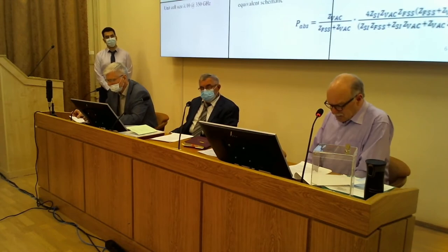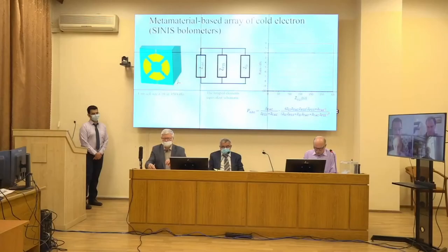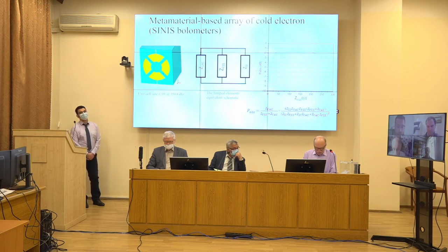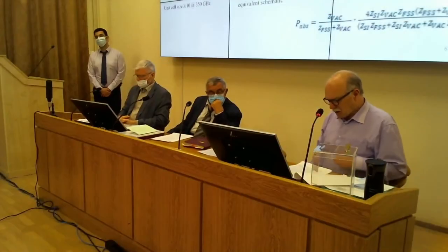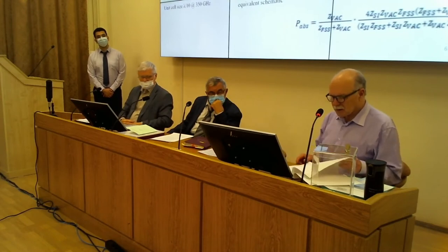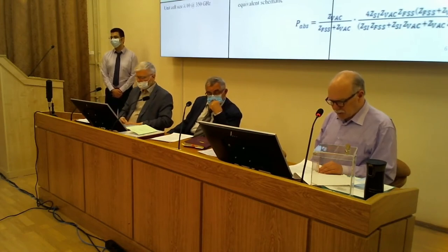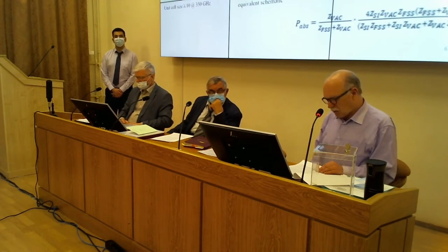The disadvantage of the dissertation includes some typos and grammatical errors in the text. In addition, the dissertation does not address the oxidation issue of Ag films, which are used as a dual-band plasmonic absorber. Despite the fact that these Ag films are coated with SiO2 dielectric, the edges of the films are not passivated, which will lead to degradation due to oxidation. As a result, the dissertation is original, new, and useful for specialists in the field, and related to problems that are being worked on at the Moscow Institute of Physics and Technology.